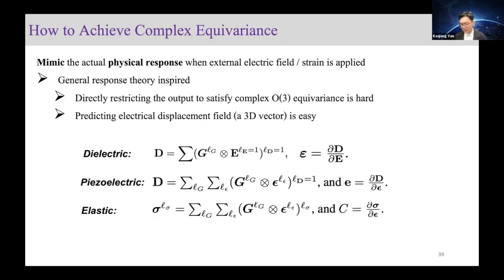And to predict the matrix form complex tensors, instead of directly forming this kind of matrix or tensor, we mimic the physical response that these tensors describe and use the gradient to directly obtain the matrix form. This is more favorable because directly restricting the output to satisfy the equivariance is hard, but predicting some dielectric electrical displacement field like vector D is relatively easy. And by taking the outer electric field E as a conditional input, the dielectric tensor can be directly obtained by the gradient.